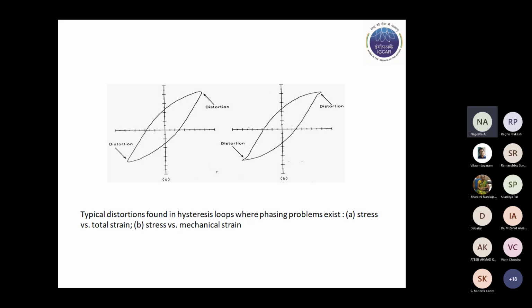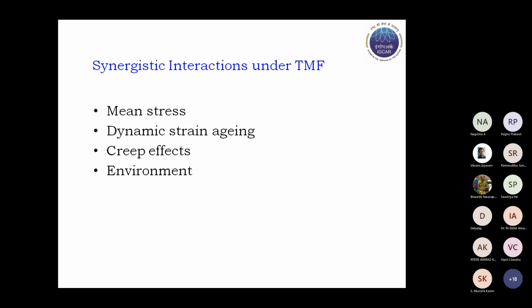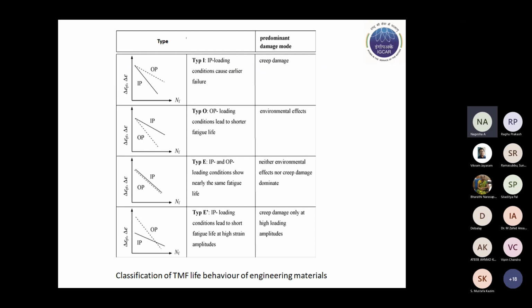So this kind of distortion also manifests in the hysteresis loops, wherein tips can be seen to be either blunted or heavily distorted. So what we have studied, we have given stress on the different aspects during the testing. Factors such as mean stress, dynamic strain aging, creep effects, and environmental effects, etc., have been investigated systematically.